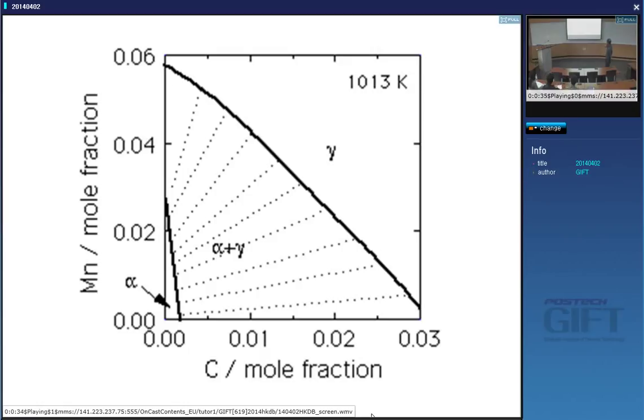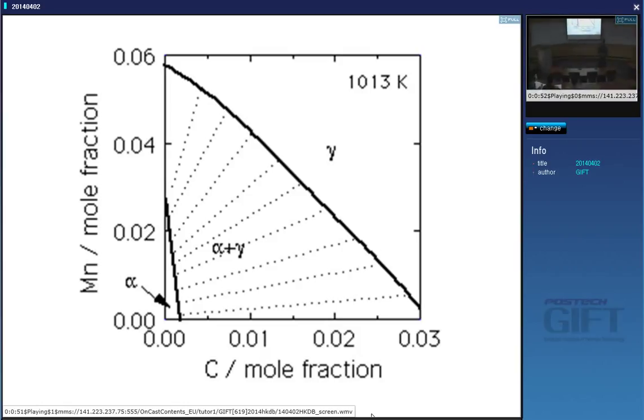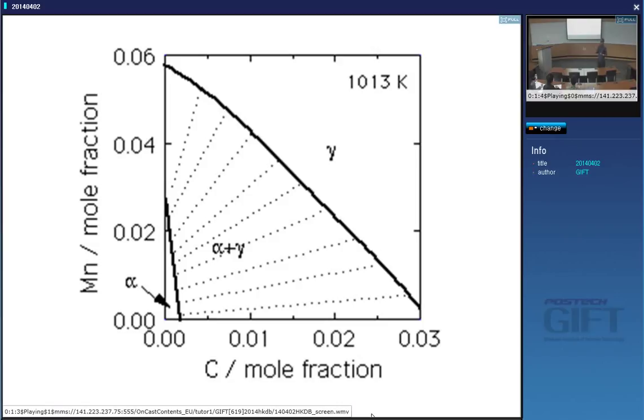What I hope to show you is that during growth, even if my alloy composition lies here, I can pick any of these tie lines to control the composition at the interface. Eventually those tie lines will change as growth happens to pass through the alloy of interest. But at the beginning it can pick any of those tie lines to ensure that the manganese can diffuse together with the carbon and maintain local equilibrium. So we have freedom to pick any tie line in that phase field to satisfy the diffusion equations.